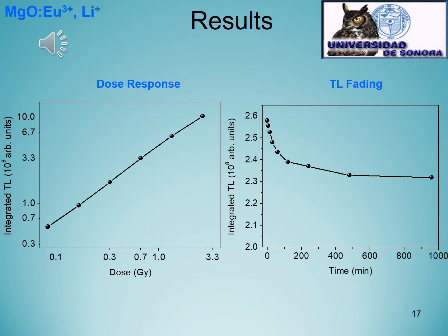For this material we can consider that the useful range is for low doses, namely personal dosimetry or environmental dosimetry, for example. In the case of TL fading, we can observe for this decay curve on the right that this material showed an asymptotic behavior, which means that the signal is stable regarding the time of storage, which is also a very desirable feature for TL dosimetry.